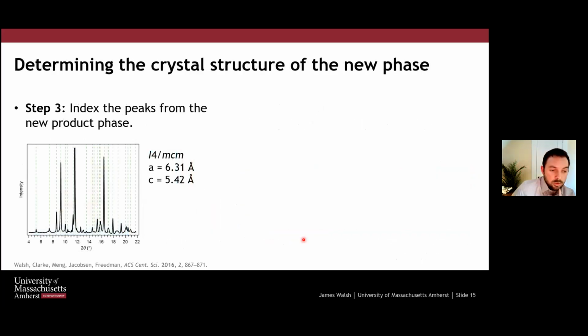You find a spot that has a good conversion and you index those peaks. And so this is something that's not trivial. To be able to index a phase, you usually need pretty good data. At the synchrotron, you can get that. Because we have relatively wide conical apertures and high energy, we actually get a lot of the reciprocal space measured on our detector, enough peaks to be able to do this kind of analysis. And so what we find in this particular case is that we can index to this tetragonal space group I4/mcm. We can index the unit cell parameters.